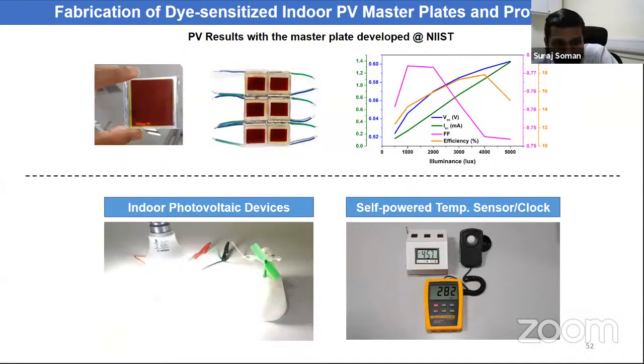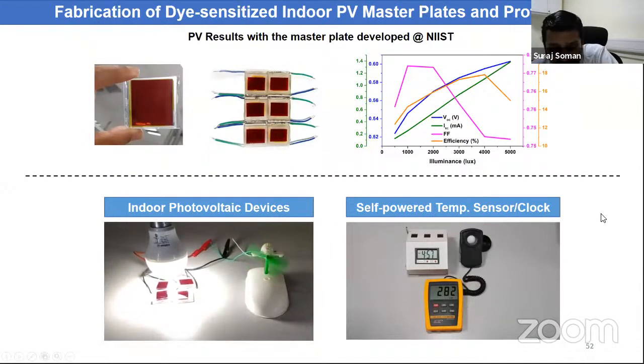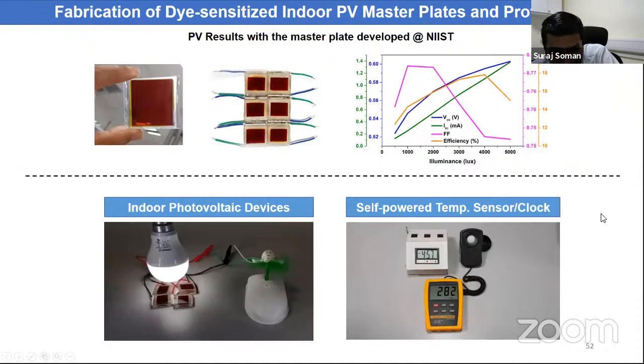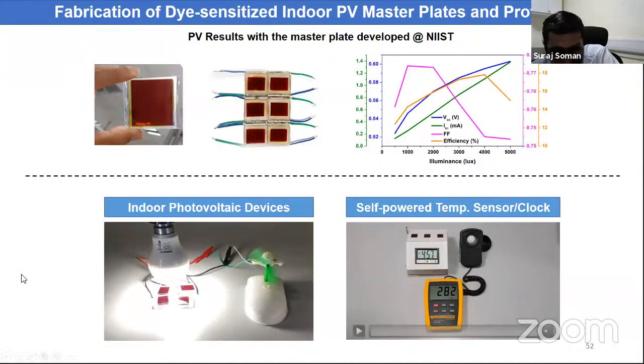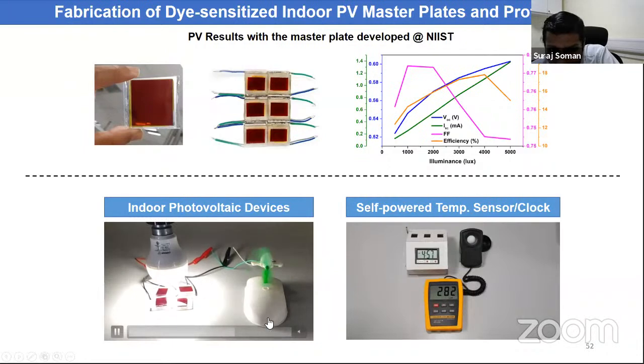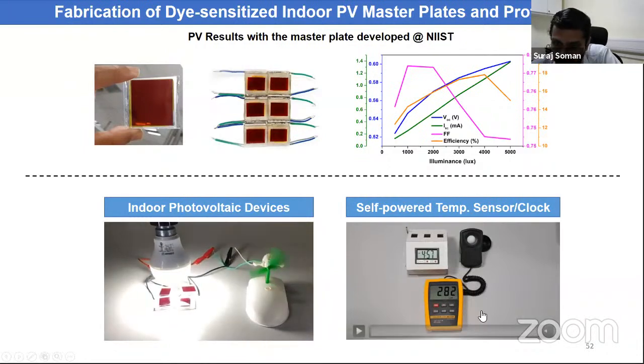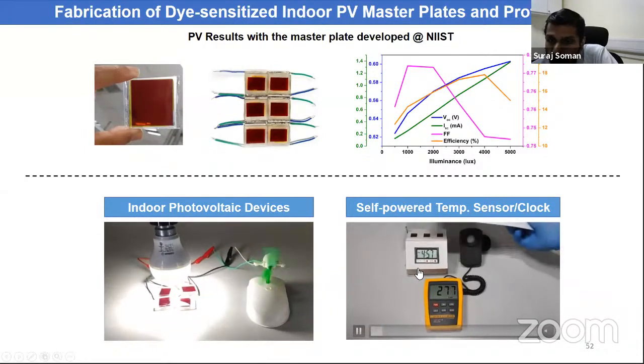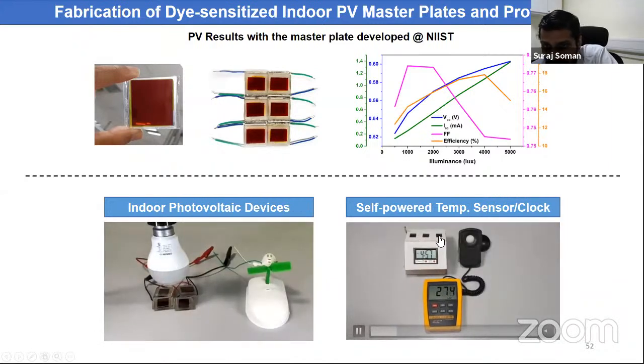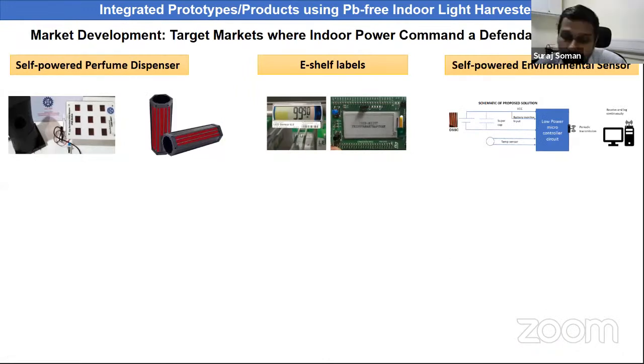This is one of the master plates that we have developed in the lab, which gives around 16 to 17% efficiency in standard indoor conditions. And you can see an LED light powering something over there. To the right, what you see here is a clock and a temperature sensor, and it has three small solar cells connected in series. And you can see the lux, right? It's less than 300 lux there. And with such low intensity, it is able to power these kinds of sensors and actuators truly independently.